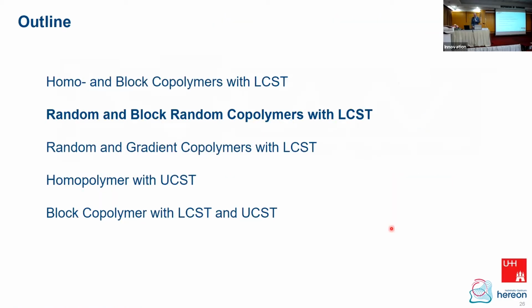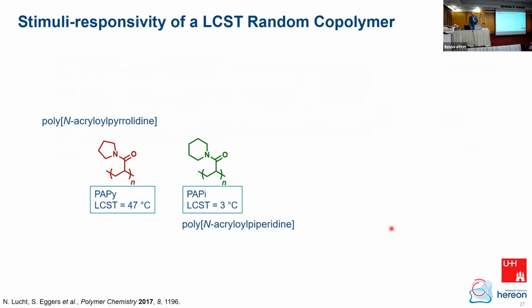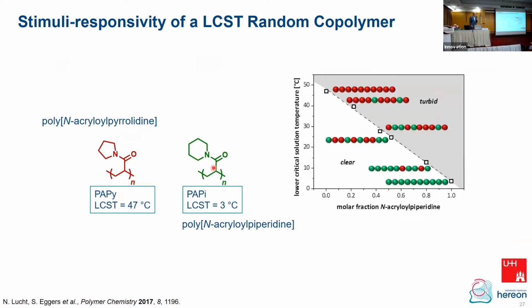Okay, let me come to the next part, about random and block random copolymers with an LCST. Here are these two polymers I introduced before, with very different cloud points by themselves. Now when you combine the two monomers on a molar ratio, this is the mole fraction axis, you can linearly calculate the cloud point of the resulting polymer. And the molecular weight dependence is very weak. So just to add that, molecular weight is not having a big influence. So basically a linear, nice behavior. And we also get very nice random copolymerization, so the copolymerization parameters are basically one for both systems. So it's very, very easy.